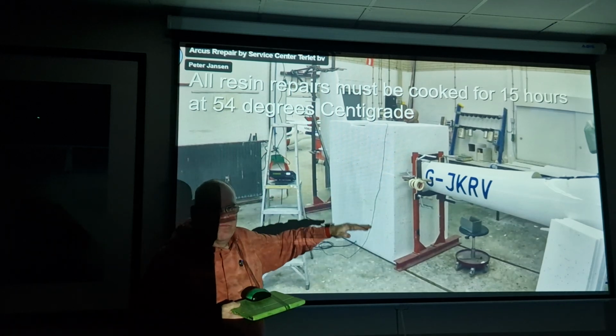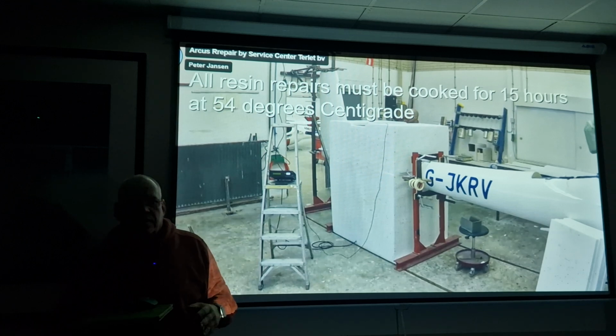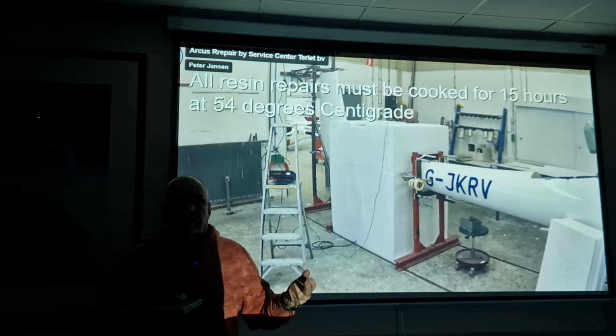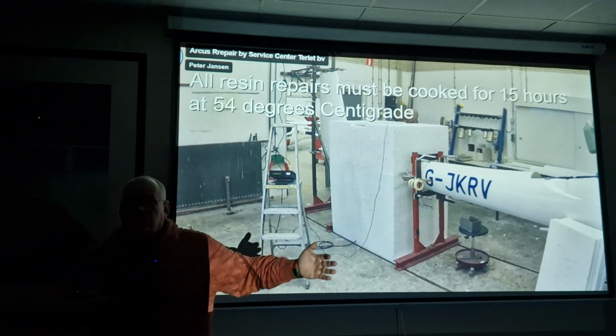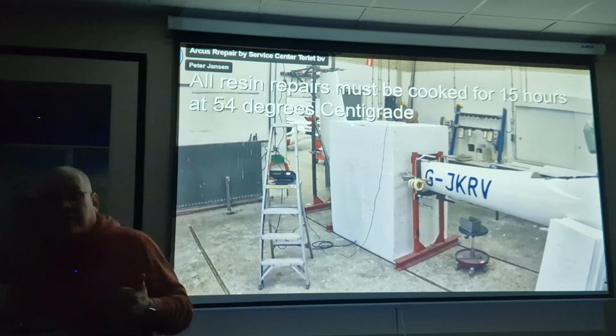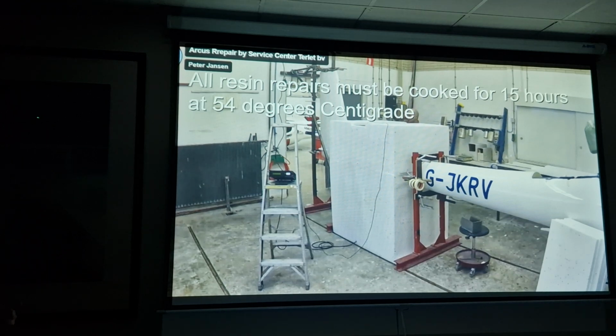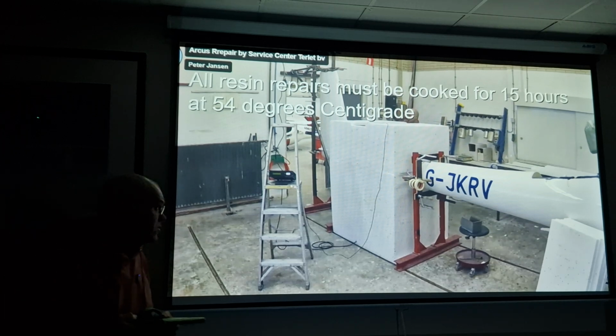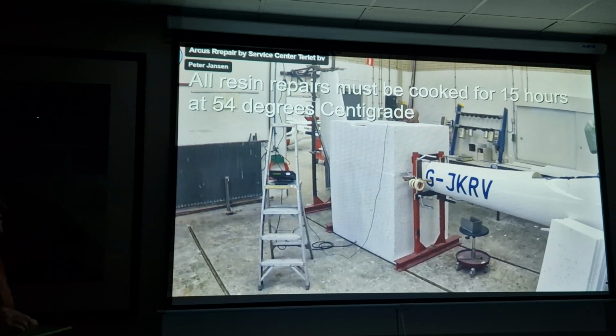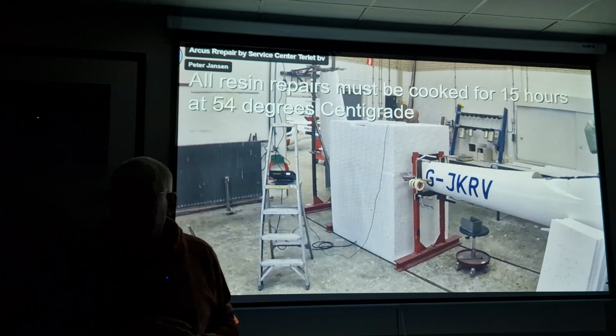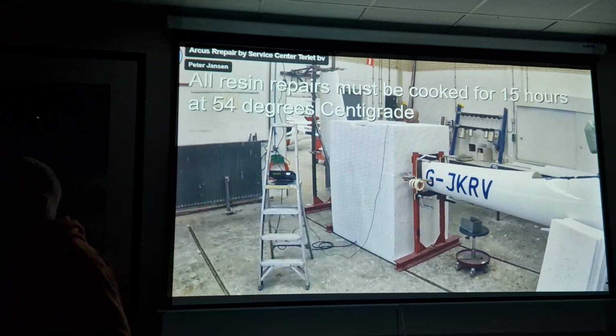And they're all vacuum formed, so you need to put it in an oven at 160 degrees. It might be a 30 or 40 foot long part, so you're looking at an oven the size of this room quite easily. And it has to be pressurized to 15 psi at least, that sort of area. So in terms of tooling, it can be quite expensive. If you ever go down to South Down Aero Services, they've got some massive ovens that are much bigger than this room, or did have, I don't know if they still have. They were making bits for Airbus and stuff like that. If you did that, you could make a glider 25% lighter and stiffer. But it would be virtually impossible to repair unless you had the tooling. So they don't tend to repair them, they tend to replace them. But it can be done.